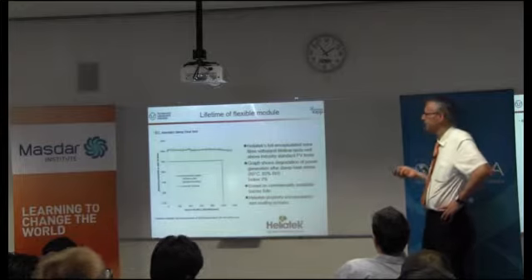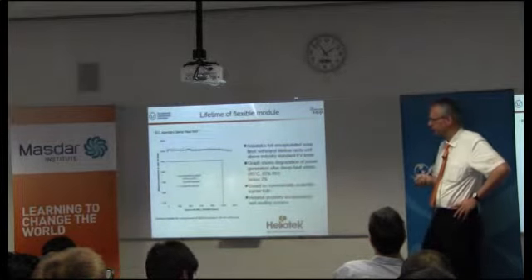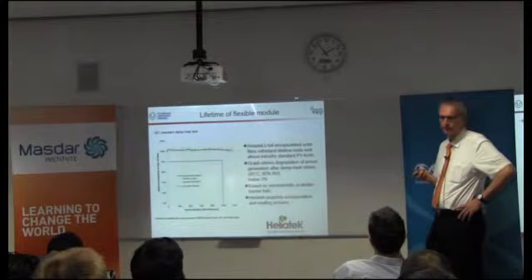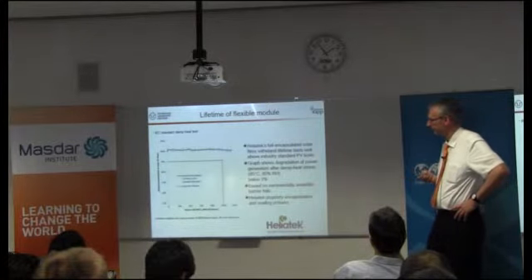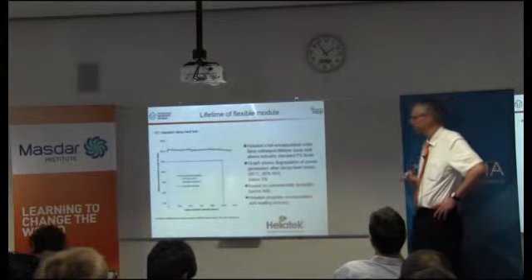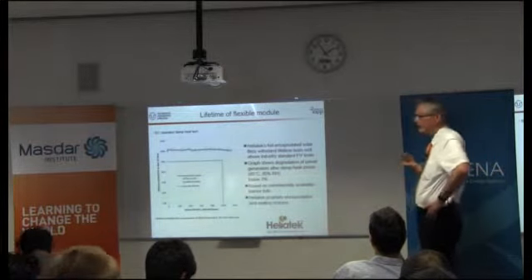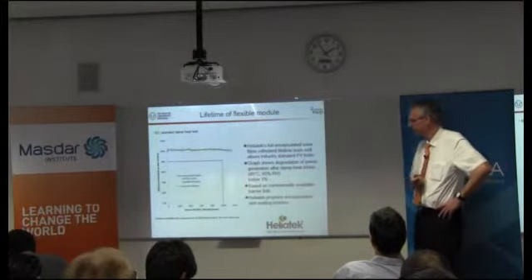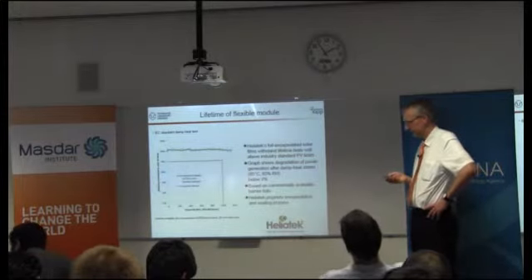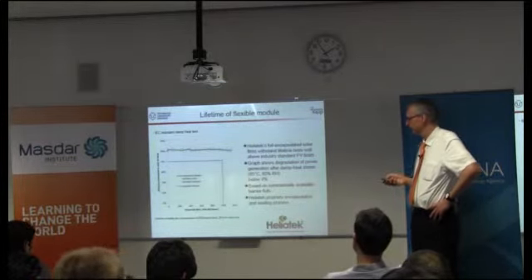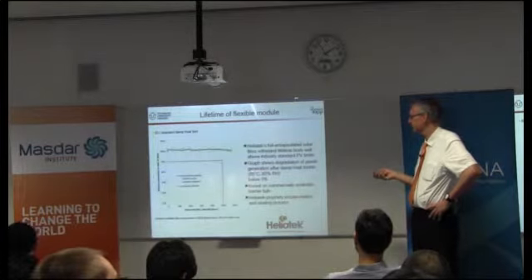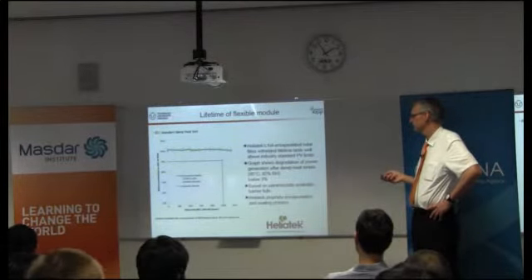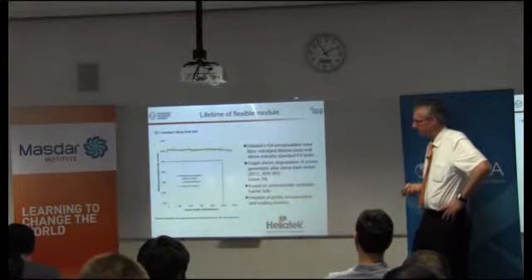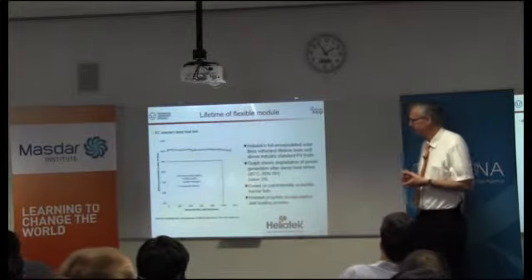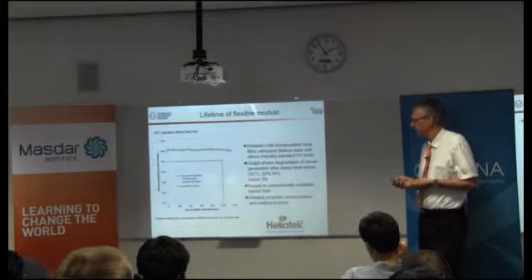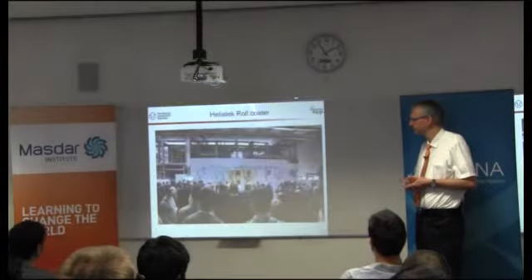And at the moment the total outdoor lifetime should be on the order of 10 years for such modules, and the goal is in the next few years to get it to 20 years, which is what is typically expected by customers. So at least the perspective is there that organics can reach these long lifetimes needed, but there's still more work to be done, especially these encapsulation foils which are used, these barrier foils. They are at the moment way too expensive, and we have to find cheaper ways to produce them.